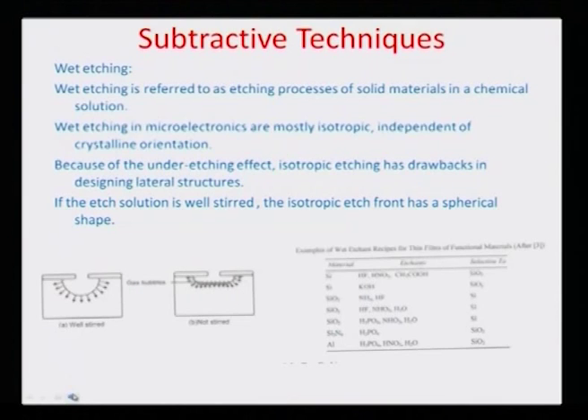So let's look at isotropic etching. As I mentioned before, the etchant is able to remove or erode away material at a uniform or homogeneous rate in all directions. This, for example, is an illustration where there is an etch protective layer, which is highlighted by the red pen here. This window in the etch protective layer gives the fluid access to start etching away the material underneath the protective layer. Because it is a homogeneous process, the etchant goes into this etch cavity and starts etching in all directions, resulting in this undercut.